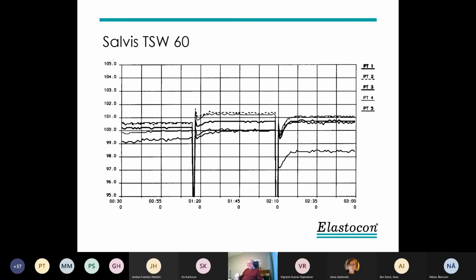You can see some measurements here. The first part of the curve is inside the oven, close to the back. Then we open the door and measure in the center of the oven. Then we open the door again and move the frame with temperature sensors to 50 millimeters behind the door. And there we see the influence of the window, that is the lowest temperature, just in the center, inside the window.